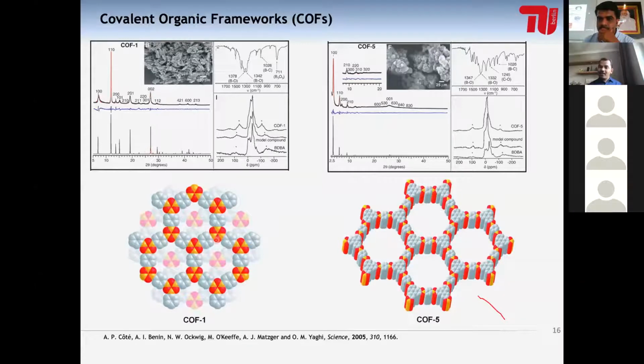Now these materials are not single crystalline, but powdery materials, which more or less look like this. We can determine the structure in a software called Materials Studio. Using computer simulation, you can determine the powder XRD of this particular material and compare it with the PXRD of your material which you have got experimentally, and check what the difference is. This can even be characterized further by FTIR as well as 13C NMR analysis. And this was the case for COF-1, where it was seen that these materials have a crystalline eclipsed structure.